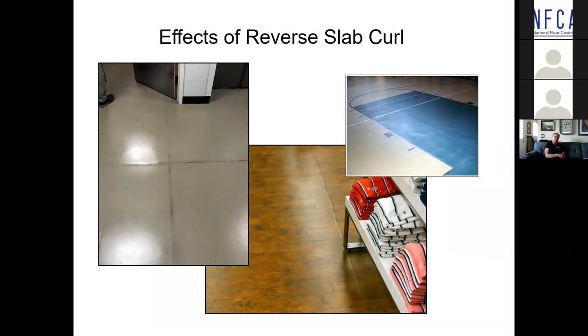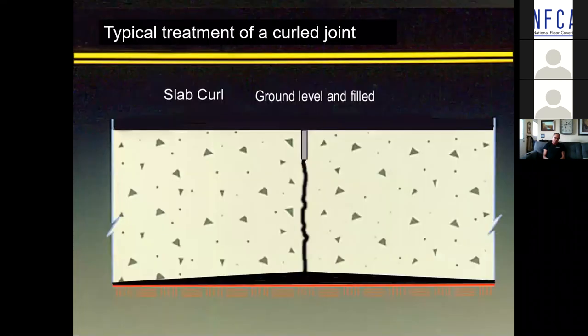The stresses subside and it puts whatever is in the joint, whether it's a joint filler material or semi-rigid material, into compression. And you can see it in all three of these pictures where the slab sections that were curled at the joints have now gone back down and put what's in it in compression. Here's what it looks like. What's the standard treatment?